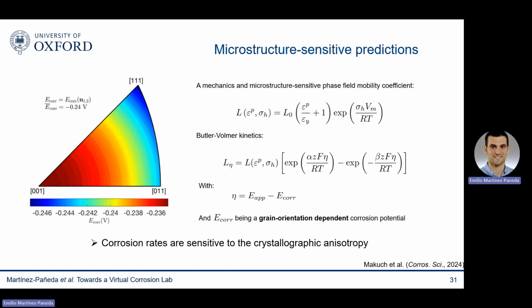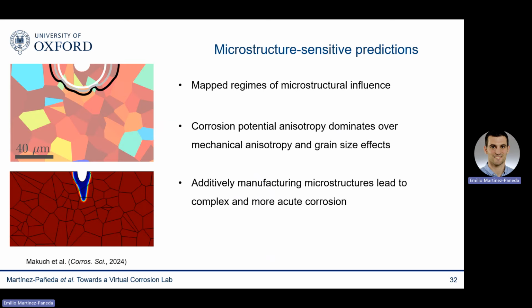So we take experimental data for different crystal orientations and define grain orientation dependent potential. And then there's many things that you can do with this microstructural enriched model. For example, you could combine it with EBSD images to look at real microstructures. In our case, what we did is to learn these things that you see here.